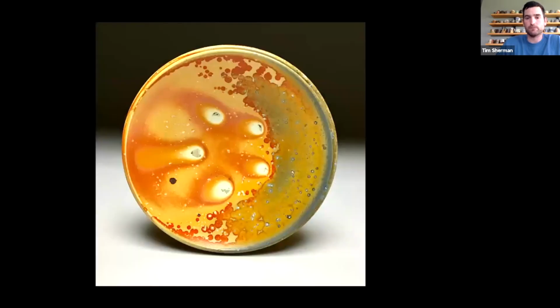Similar thing, just a very unique surface with no glaze added at all, just the time in the kiln, the type of clay, and the fuel too. This is when we were burning a ton of poplar when it was really accessible to me. And I think that had a big impact because it was so full of water. Our firings were very different than they are now. The colors are just not the same. And I kind of credit most of that to having cords and cords of poplar that we were going through.